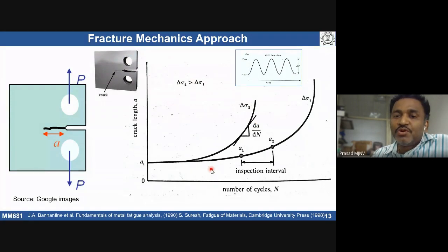If I take two different points, between any two points, the crack propagation rate under cyclic loading condition is basically given by da/dN. If we take two adjacent points and get a slope, the slope tells how the crack length is changing as a function of number of cycles. So da/dN is called the crack growth rate under cyclic loading conditions.